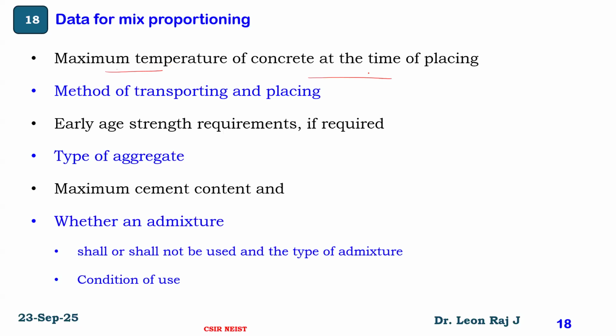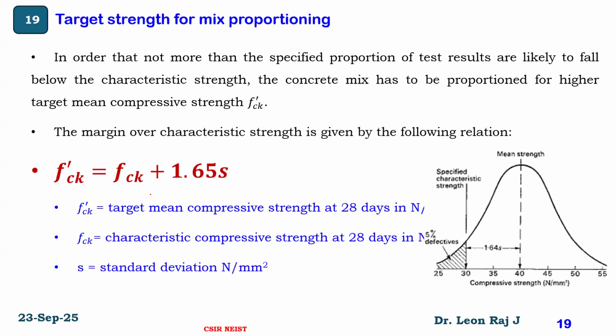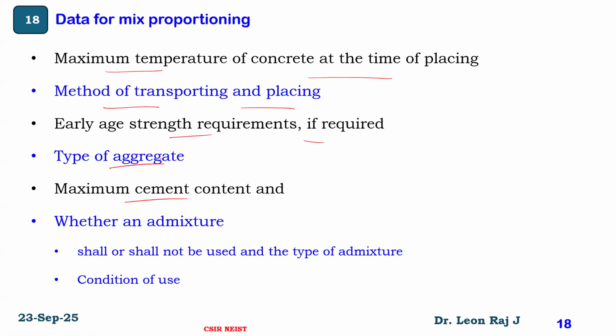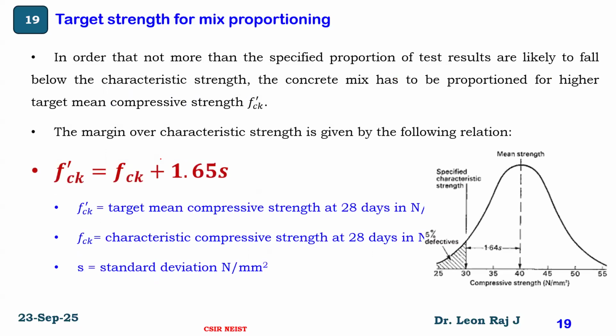The maximum temperature of the concrete at the time of placing is required to measure the workability, method of transportation and placing. For example, what is the mode of transportation of ready mix concrete (RMC)? Then early age strength requirements if required. Then type of aggregate, then maximum cement content, and whether an admixture is required or not, the conditions of use, then target strength for mix proportioning. What is the target mean strength? So target mean strength is nothing but fck plus 1.65 into S.